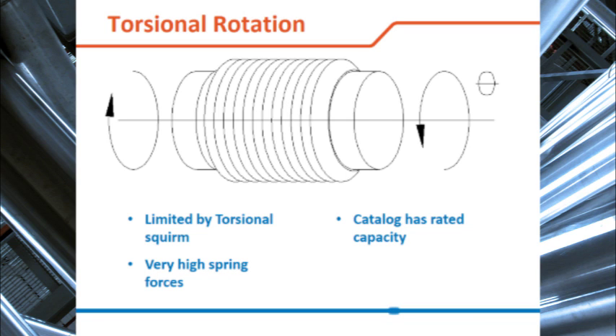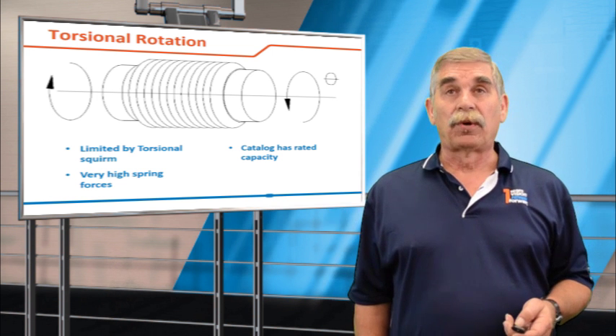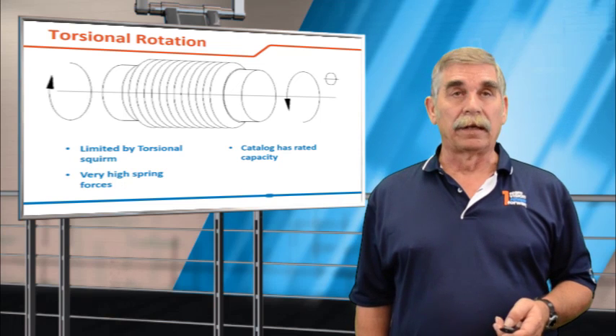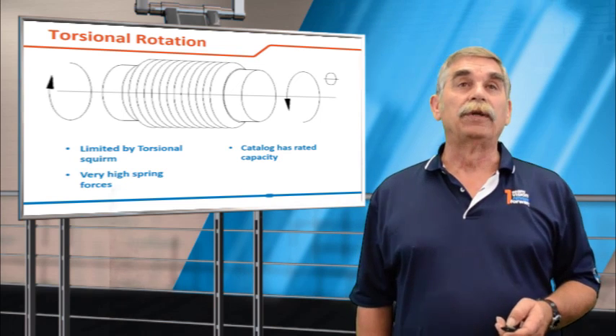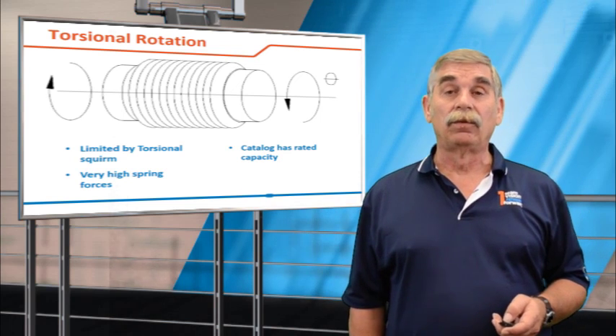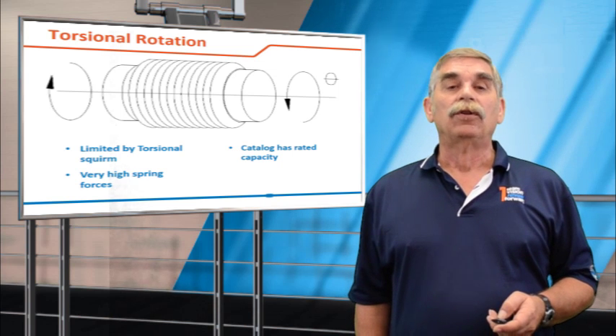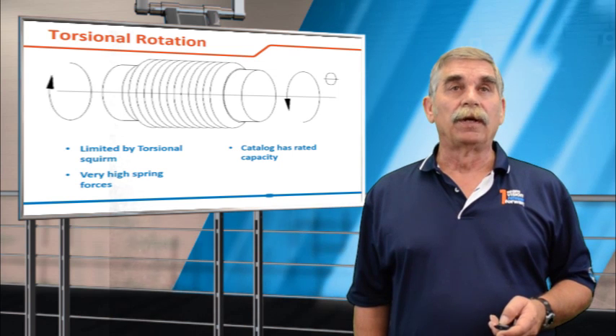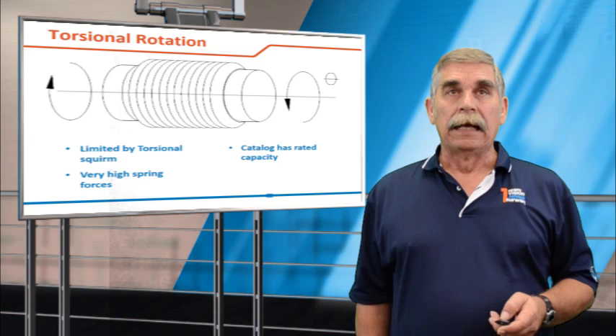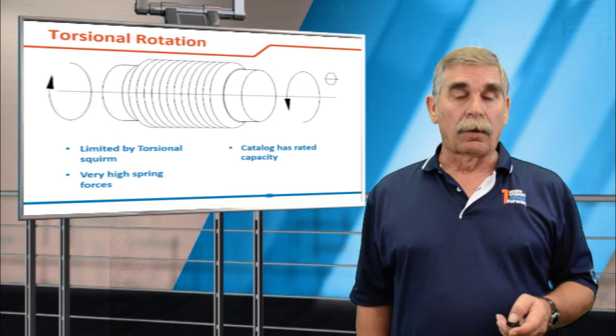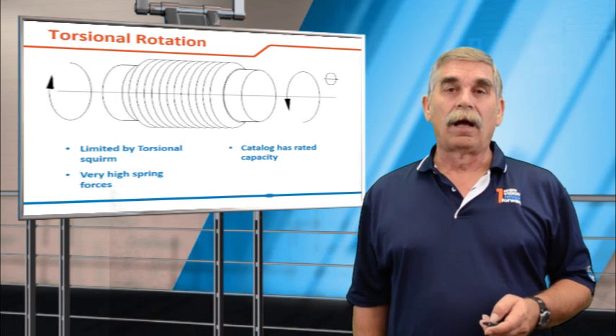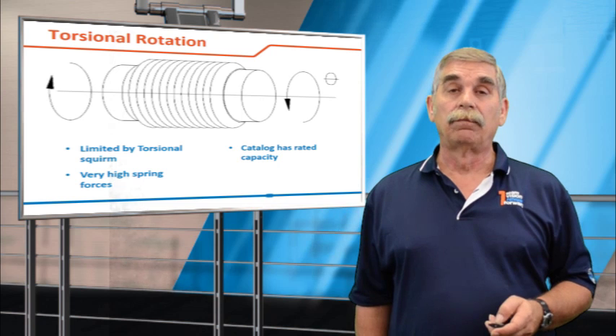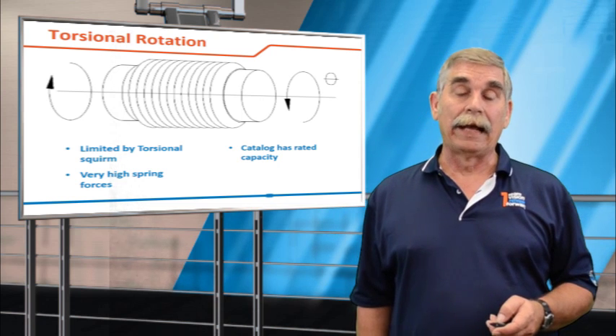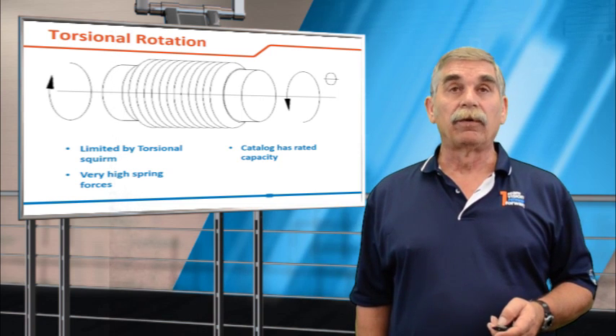Torsion is the actual twisting of the metal bellows by the pipe system. And there is a significant problem, which is torsional instability. And as a result, we generally recommend not to design your system to have torsion on a metal bellows. You get a very high spring force, and instability is our primary concern. Our catalog does, however, have published rated torsional angulations and spring rates.